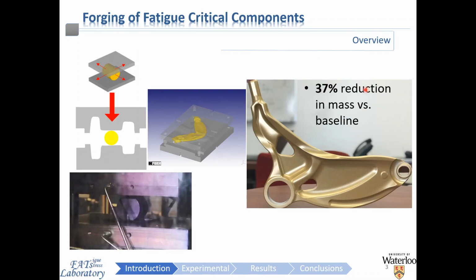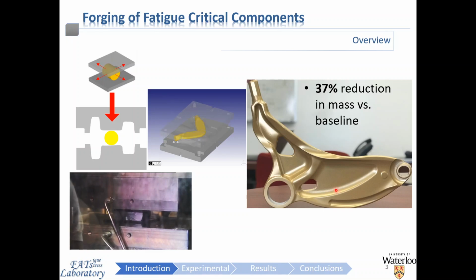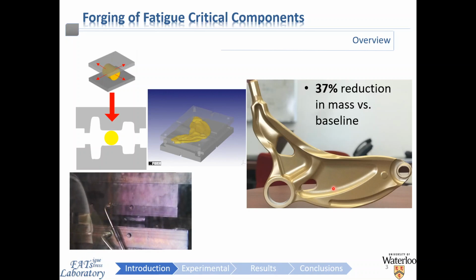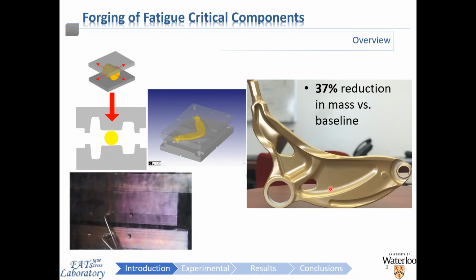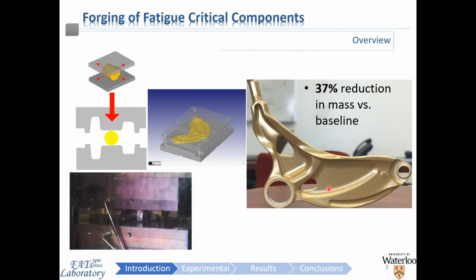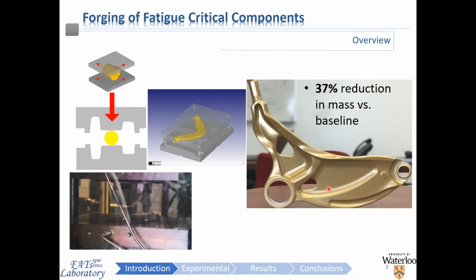Somewhat of a prelude to the talk, I like to present this photo of the final component which was produced as part of this work, not only because it might be visually appealing, but to emphasize the main objective of the work, which was vehicle lightweighting. We targeted a fatigue-critical automotive suspension component, for which we were able to achieve a 37% reduction in mass versus the aluminum baseline component. This type of paradigm-shifting improvement was only possible due to the experimental method which was adopted to optimize all facets of the research process.